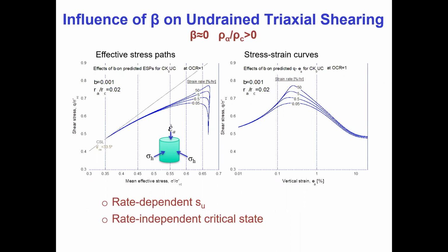This is the stress path. Don't be too alarmed at the look of the stress-strain curve. I just drew it on a log scale, which pulls it out. Undrained strength is the peak value. Critical state is this value up here. And what you can see in this figure is us choosing a set of parameters for modeling in clay where we see the undrained strength changing, but this critical state is not changing. And as expected, this is one with a very low beta value.